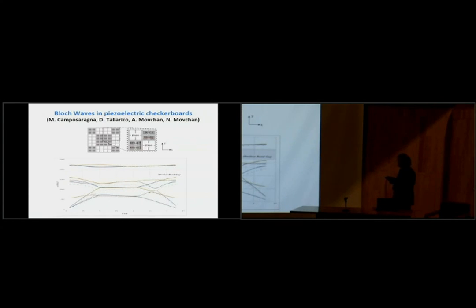But if your polarization is the same on both sides of the interface, there isn't much change that you observe for this frequency range. But as soon as you change the polarization of the gray materials so that it's different from the direction of polarization of the white material, then you have a difference. So here you have solid lines, then you have dotted lines, which are hardly visible because they nearly coincide with the solid lines, and dashed dotted lines that occur when you change the polarization. So this interfacial effect gives you quite a lot in terms of control of this kind of structures, and it's a genuine dynamic effect.